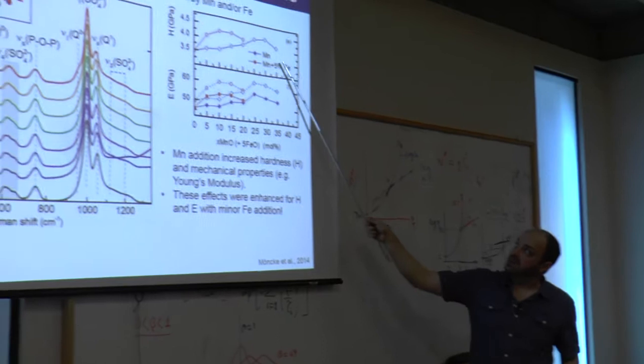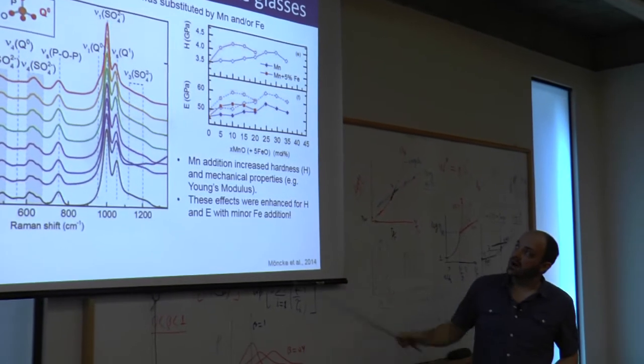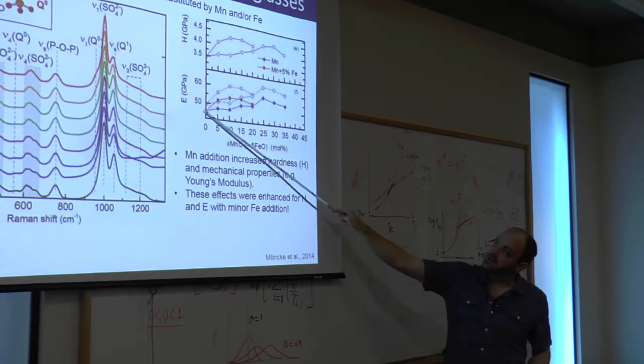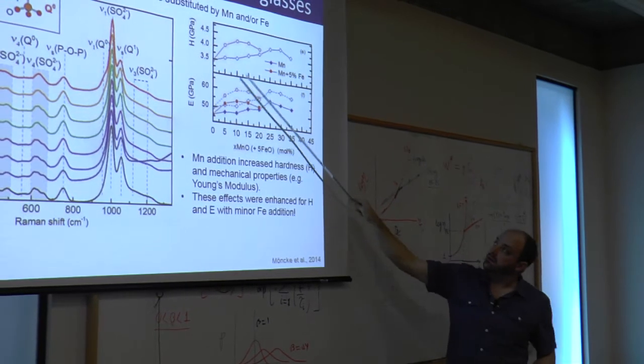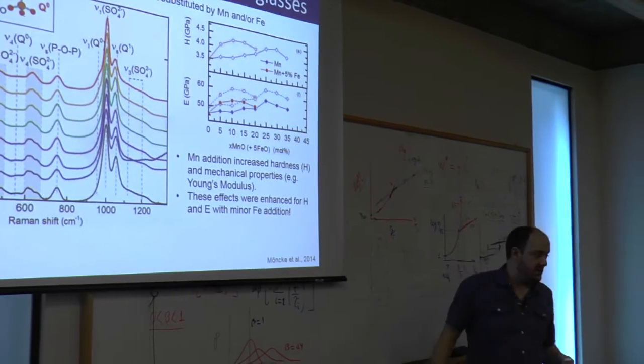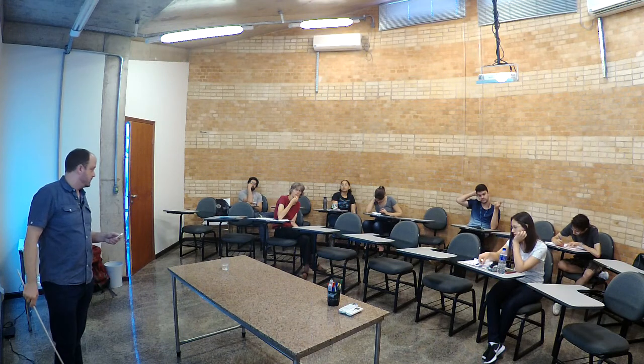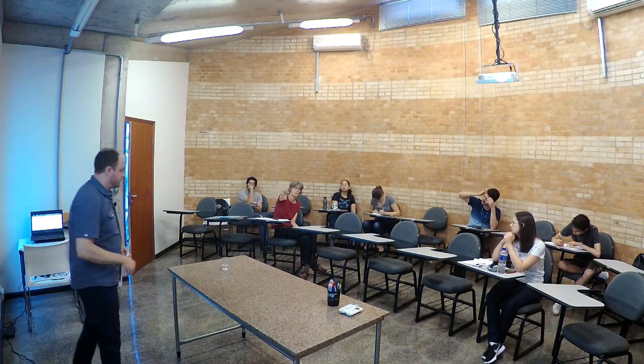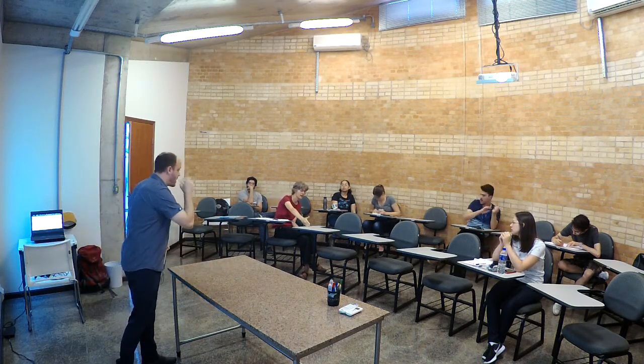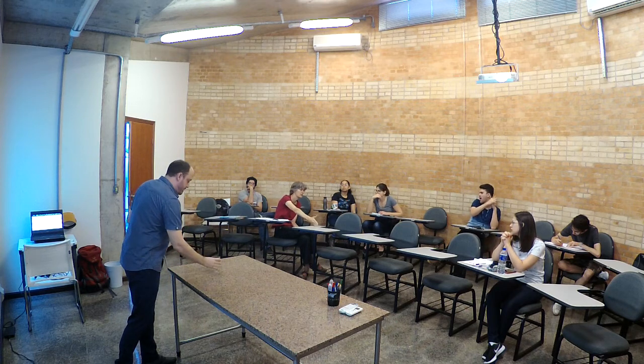If you add, in addition to the manganese, also some iron, you can enhance these properties at very, very low manganese and iron content. And a lot in this paper is on manganese and iron. They are both in the divalent and trivalent state. So we tried to stay reduced and have only 2+, but we didn't succeed. So we also do have a lot of trivalent. If we do have trivalent, then we add more oxygen, then we do something to the network.